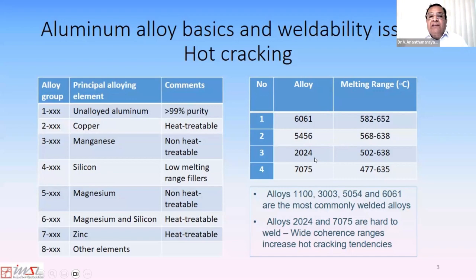And if you look at the two alloys below, the 2000 series and 7000 series alloys, the melting ranges are more than 100 degrees Celsius, more like 130 in the case of 2024, and almost 160 degrees Celsius in the case of 7075. And the difference between the solidus and the liquidus is called the coherence range. And the higher the coherence range, the higher the tendency for hot cracking of a weld metal as it solidifies. That's one of the main reasons why these two alloys are not considered weldable.